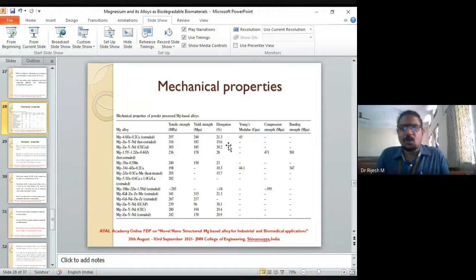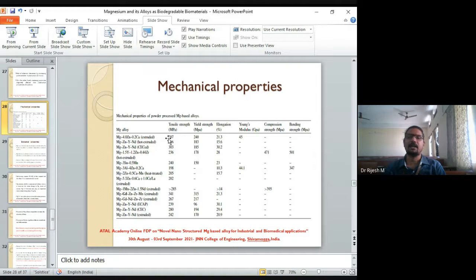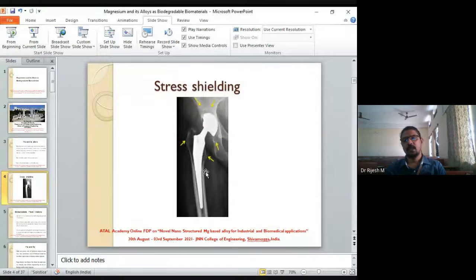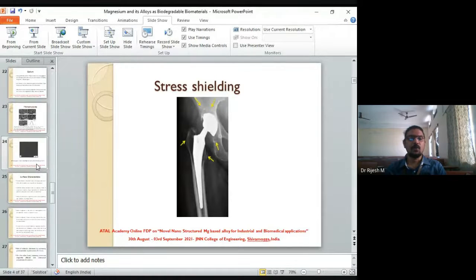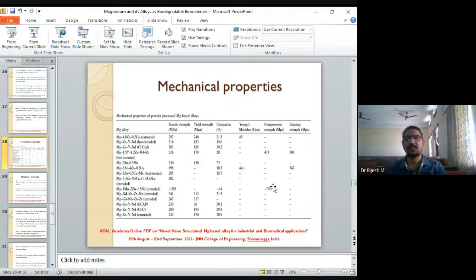Our major problem in the previous talk was, since the material is lightweight, how can we increase the strength to a larger extent? But here that is not the case. Here we do not want the strength to be that high. If the strength is very high, you will have a problem like stress shielding. So I don't want this high stress. If the stress is very close to the value of the cortical bone, that is more than enough for me. Got it. So I literally do not go for all these materials. I go for a powder metallurgical product. Okay.